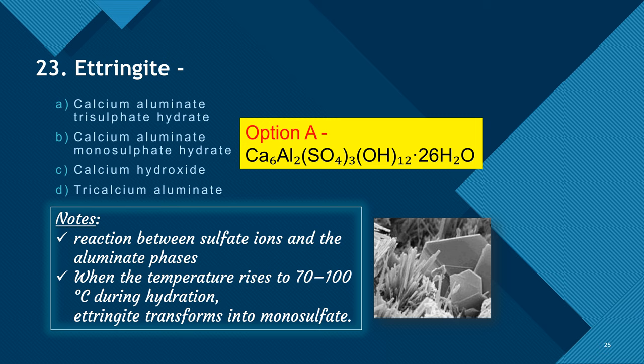If this ettringite is actually trisulfate hydrate, when we raise the temperature to like 70 to 100 degrees Celsius during the hydration process, this ettringite will transform to a monosulfate compound, and that will be dangerous because it will cause deterioration of the concrete. So ettringite has to be in such a way that it should not transform to monosulfate. So temperature has to be controlled. Ettringite is nothing but calcium aluminate trisulfate hydrate. Now let's move on to the 24th question.